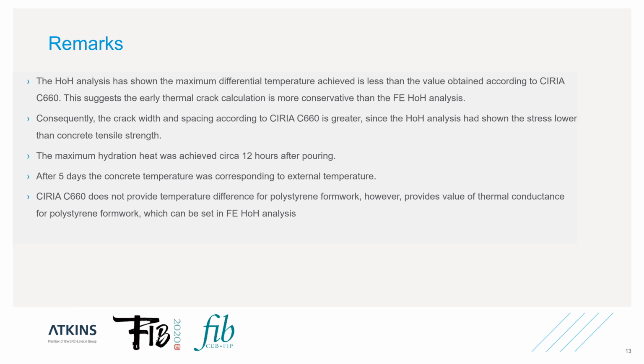The FE HOH analysis has shown that the maximum differential temperature achieved is less than the value obtained according to CIRIA C660. This suggests the early thermal crack calculation is more conservative than the FE HOH analysis. Consequently, the crack width and spacing according to CIRIA C660 is greater, since the HOH analysis had shown the stress lower than concrete tensile strength. The maximum hydration heat was achieved circa 12 hours after pouring. After 5 days, the concrete temperature was corresponding to external temperature. CIRIA C660 does not provide temperature difference for polystyrene formwork, however it provides a value of thermal conductance for polystyrene formwork, which can be set in FE HOH analysis.